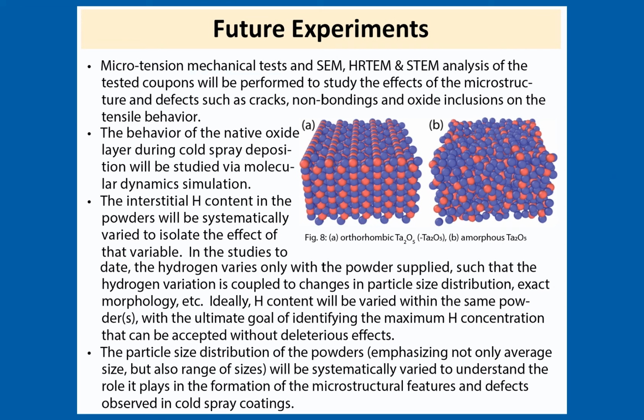Moving forward, the first step is to repeat the tests and analysis presented today, but under tension conditions. We also want to further explore the behavior of the native oxide layer during cold spray deposition through molecular dynamics simulations. And lastly, in order to deconvolute the effects of multiple variables, two different studies have been put into motion. The first one will systematically vary the interstitial hydrogen content in the powders, while the second one will systematically vary the particle size distribution of the powders.